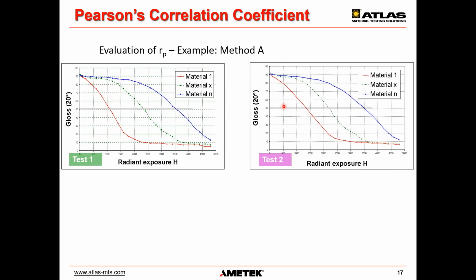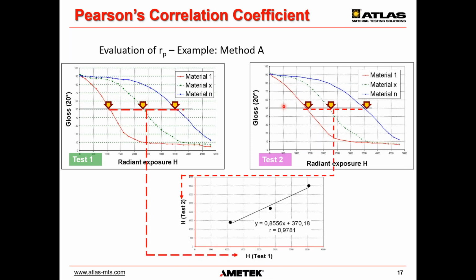However, also in our example here, we use method A. So we expose in 2 test scenarios, test 1 and test 2, 3 different materials, the same materials, of course, in both test setups. And we do the exposure until we get to a residual gloss of 50%. And then we do an evaluation with evaluation criteria, the radiant exposure it takes to get to that specific loss for the different materials. And then we can simply do a correlation between the 3 materials, and we can calculate actually the Pearson correlation coefficient. Again, we come back to that later in more detail, and it shows an almost perfect correlation.